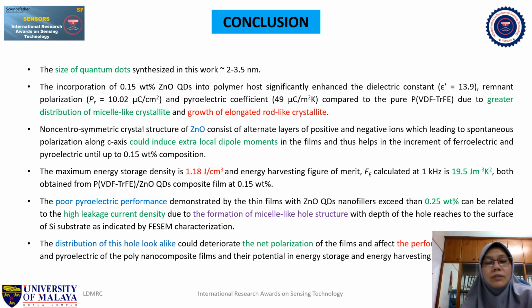The maximum energy storage density recorded is 1.18 joule per centimeter cube. The figure of merit calculated at 1 kHz is 19.5 joule per meter cube Kelvin square. Both are exhibited from the nanocomposite with 0.15 weight percentage of zinc oxide quantum dots. And we see that as the nanofiller weight percentage increases exceeding 0.25, the performance of pyroelectric deteriorates.